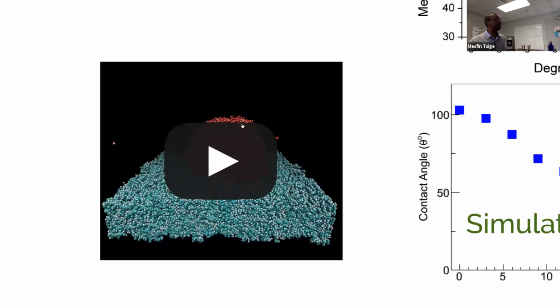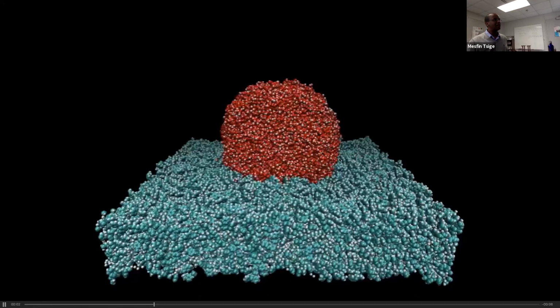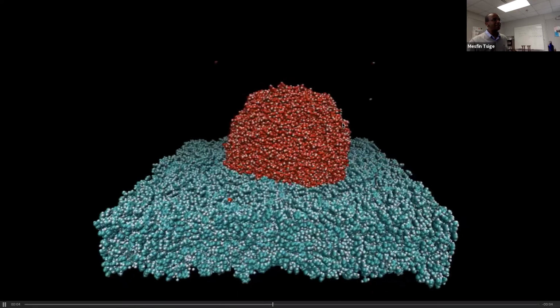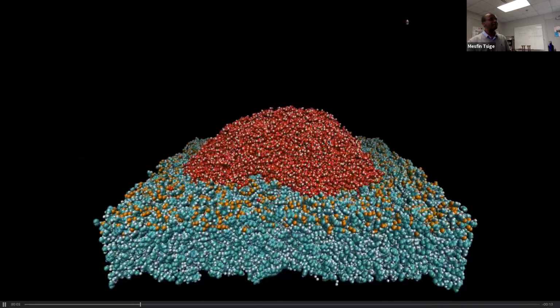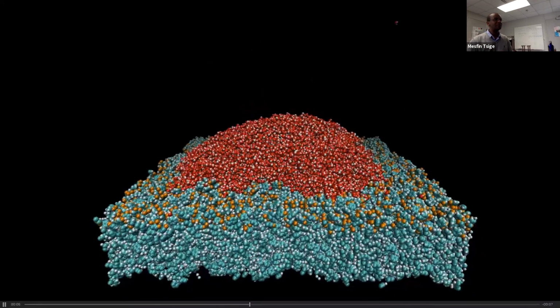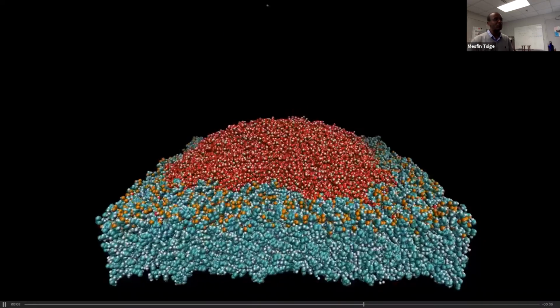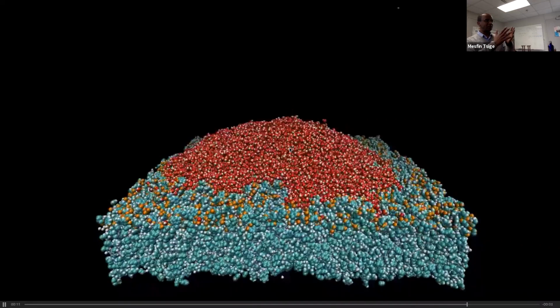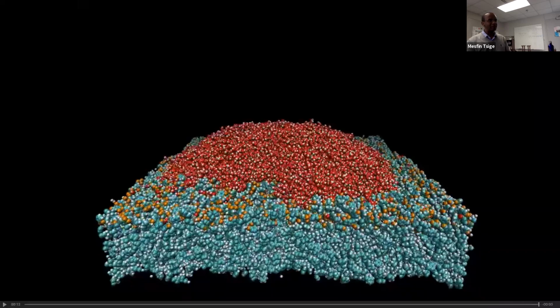The reason being we have a better control in terms of the distribution of the oxygen containing groups on the surface. This is when we have 0%, when polystyrene is not oxidized. This is what I showed you earlier. We see that 95, 96 contact angle. Whereas when we oxidize the surface, now we see that the droplet is actually wetting the surface. We see a change to a contact angle of around 40, 45 degrees. So it is spreading, and at the same time diffusing.